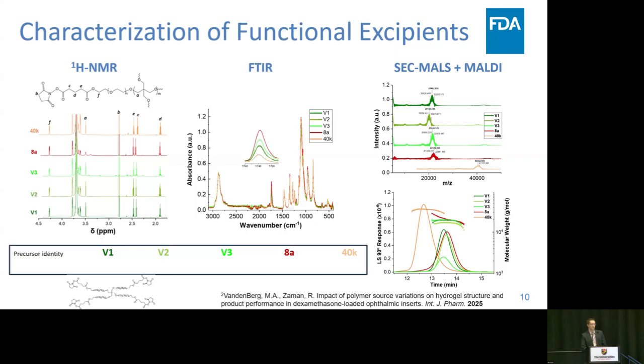And then putting those things together, we were able to come up with kind of a statistic for these that would describe the cross-linking capability of the polymers. And so this is the theoretical chemical cross-links on mass basis, which is those numbers in the bottom left. And you can see for V1, V2, they're quite similar. V3 was different than them by about 14%. And then the 8-arm and the 40K were kind of like control, or reference points to understand what if you use something that has double the cross-linking density, what if you use something that has double the molecular weight.